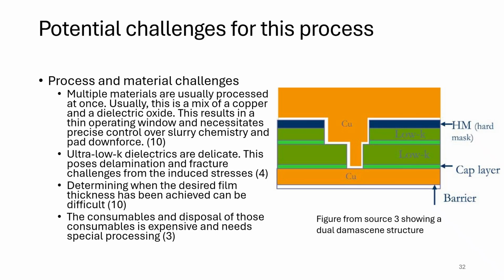On the process and material side, chemical mechanical planarization often hits a narrow operating window because we're polishing multiple materials at once. This is typically copper alongside a hard dielectric oxide, so the slurry chemistry and pad downforce have to be tuned for both materials at the same time. The use of ultra-low K dielectrics also adds risk. They're mechanically fragile, so it's easier to delaminate or fracture if the process is too aggressive.